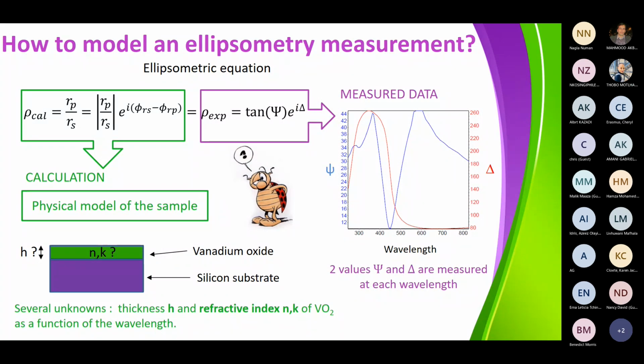Okay, to be able to calculate the theoretical ρ, we need to define the model. Here, the model is composed of a silicon substrate with a VO2 layer with a thickness h and optical properties defined by n and k. n is the real part of the refractive index, and k, the extinction coefficient linked to the absorption, is the imaginary part of the refractive index. Then, with ellipsometry, we are able to define the thickness h and the refractive index of the VO2 layer as a function of the wavelength.